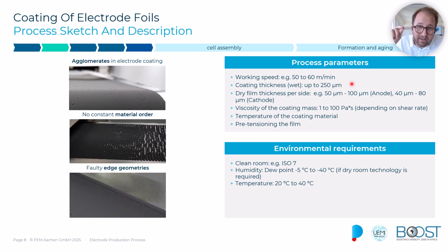So typically the foils are very thin, only a few micrometers, and on top of that you have the coating thickness, which can be up to 250 micrometers in the wet stage. Of course, after drying that would reduce a little bit, as you see here. Another interesting factor to measure is the viscosity of your slurry, making sure you have the right throughput through your slot die, and avoiding things like this here, for example, with the missing material during the coating process. This is also happening in a clean room environment normally.